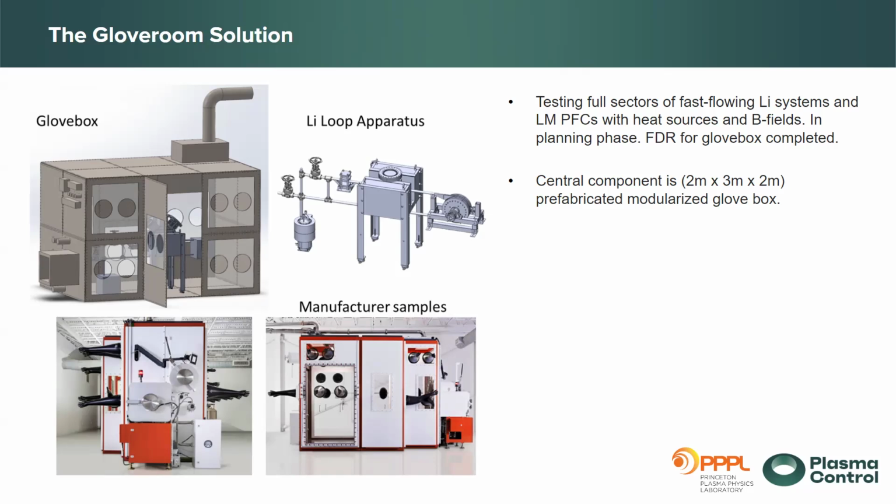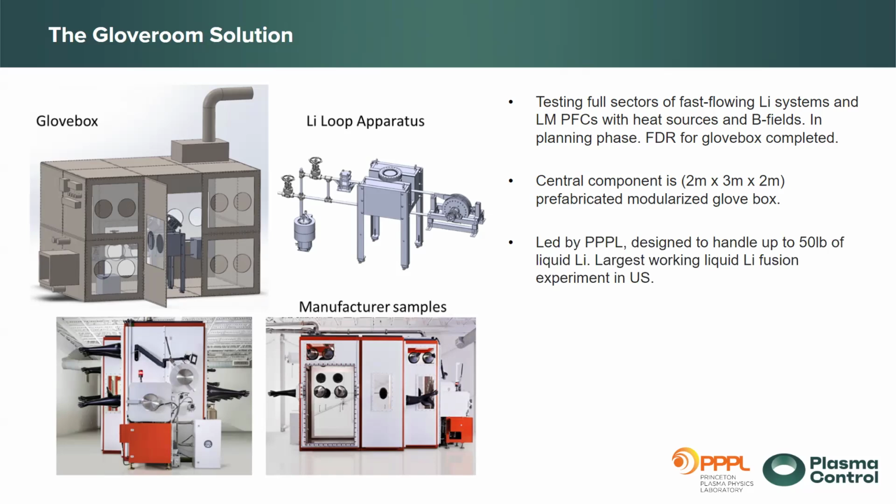But of course, it's a stainless steel Lego set, and it can handle up to 50 pounds of lithium. It will be led by PPPL. It will probably be the largest working liquid lithium fusion experiment in the US once built. The key thing to guarantee safety is that we purge argon during operations when the door is closed, to keep the moisture and oxygen level below 1,000 ppm, which has been empirically proven to be sufficient for this secondary confinement.